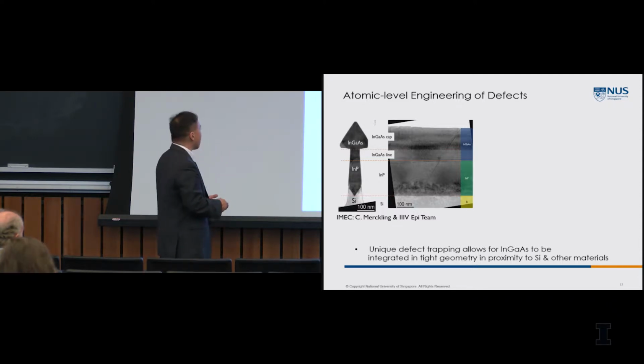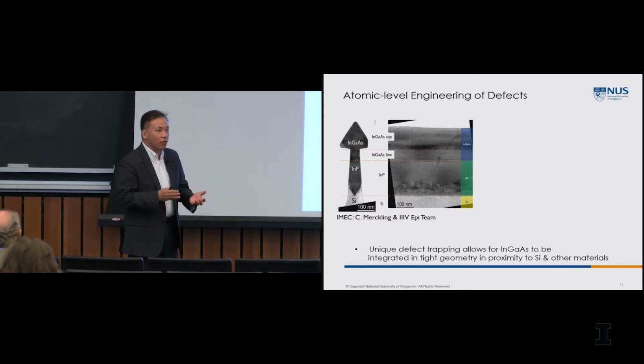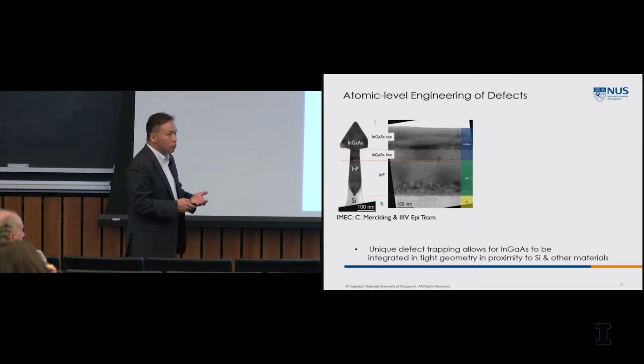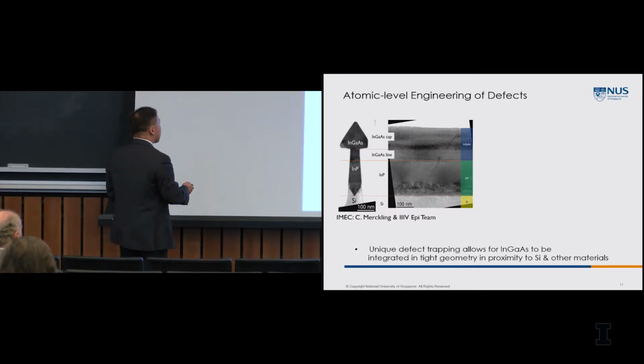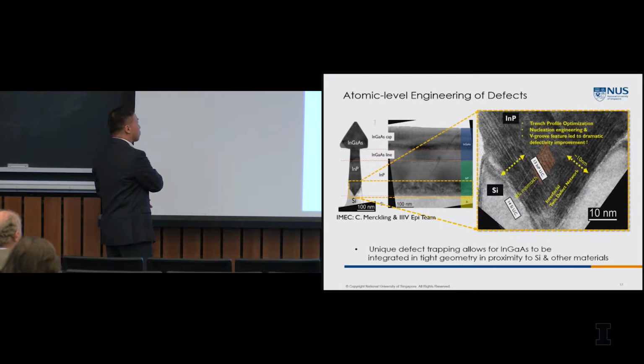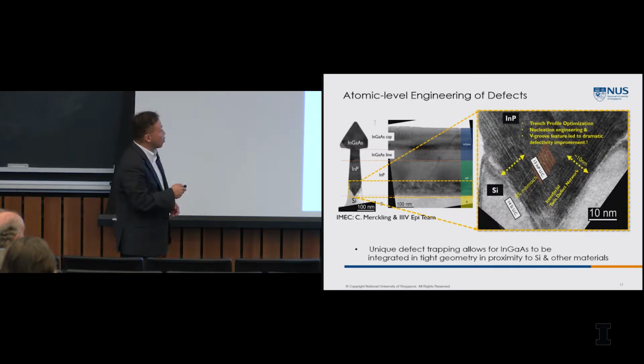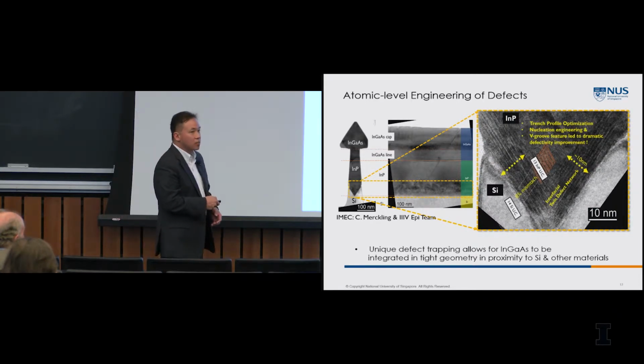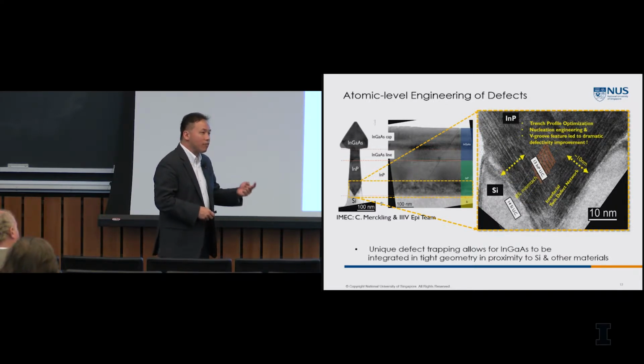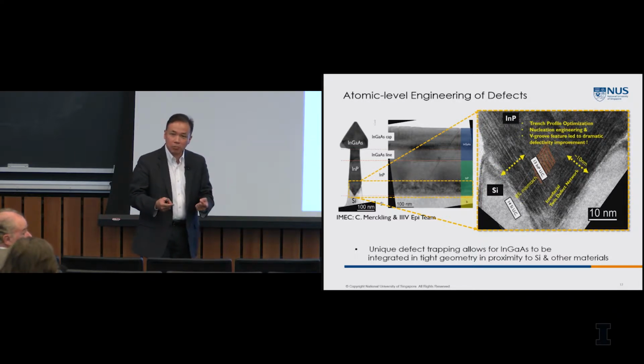Effectively, that's what happens. Now, of course, it's not that simple, because you're putting in materials that are very disparate in terms of lattice constant, and then you're going to create defects. How to engineer those defects is the work of art that we have to figure out. The way it's done is we intentionally create defects where we don't care, and then use those defects to trap the defects that are formed due to the lattice mismatch.